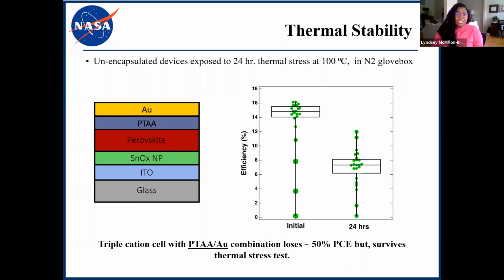In our final case, we took this unencapsulated device with PTAA and a gold electrode, and we observed that it also lost about 50% power conversion efficiency, but it did survive the thermal stress test. So this really gave us a bit of pause because we anticipated that these organic layers would flop fairly quickly. So we realized they're a bit more durable than we give them credit for, but we also acknowledge that we're going to need a lot more than 24 hours of thermal stability for our applications.